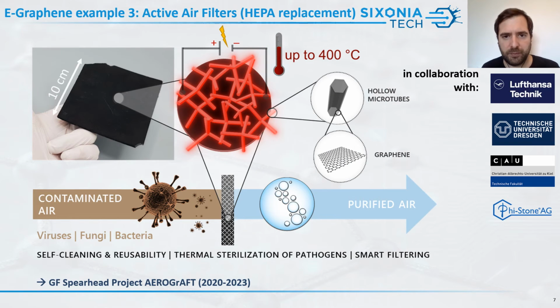What these materials can be used for is air filter materials, which we are currently developing in collaboration with different partners inside the Graphene Flagship in the Spearhead project AEROGrAFT. If you have a material that has such an intrinsic structure, it's very similar to a HEPA filter, but it's made entirely out of graphene, so you have a filter that's conductive. If you have a conductive filter, you can just apply electricity to heat it up, and this is really possible within milliseconds. We can use that to either regenerate the filter or kill any viruses and bacteria that have been filtered in this material, or also to simply monitor the filter status. So if the filter is highly loaded or it's fine and we don't have to regenerate it right now, you can easily measure that by the response to an electric signal. So this is also very exciting.